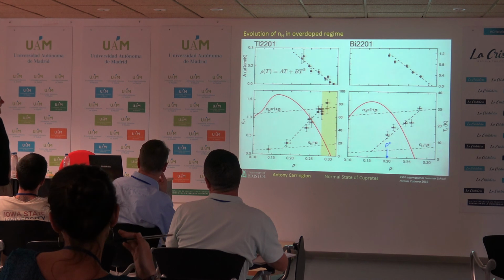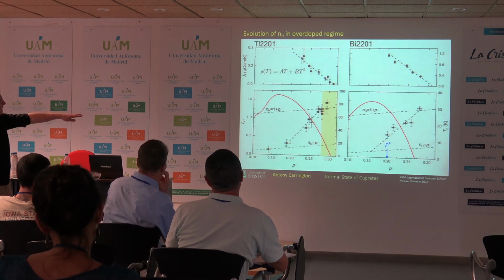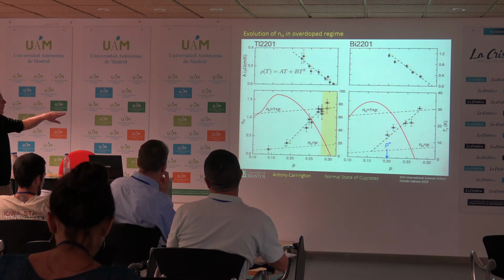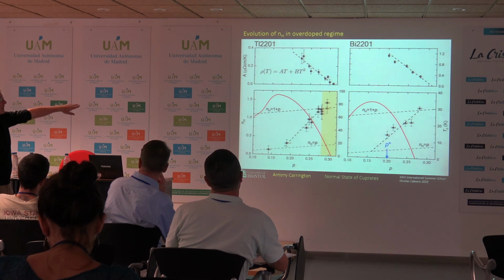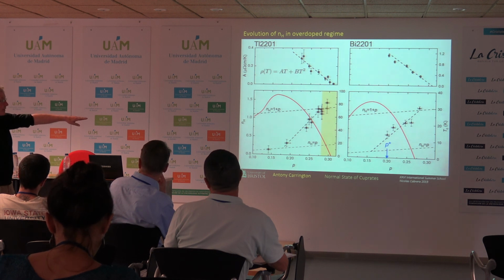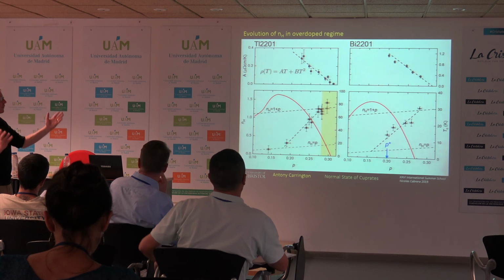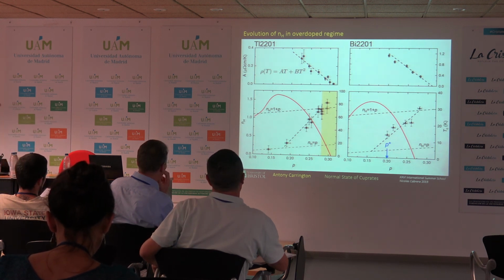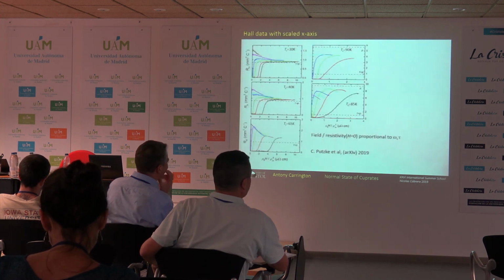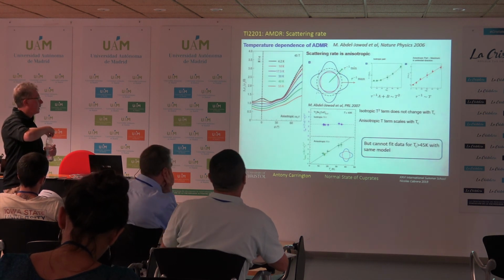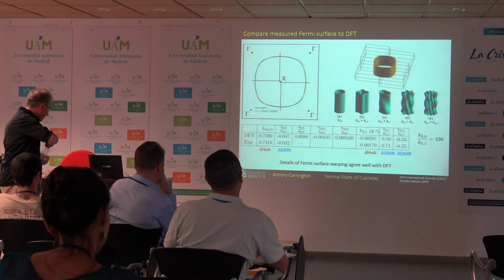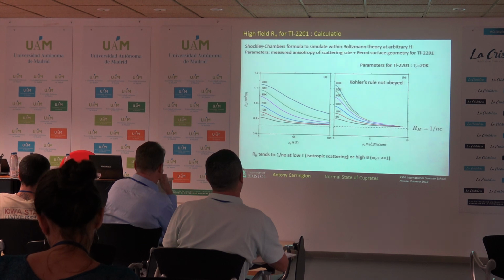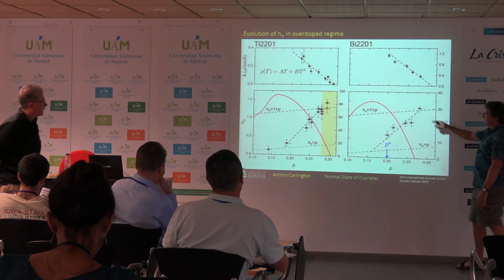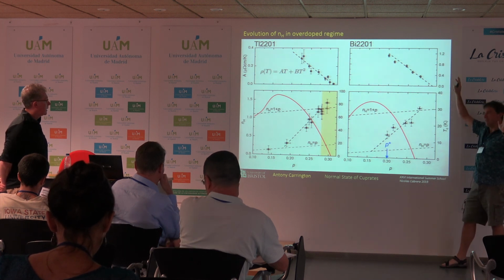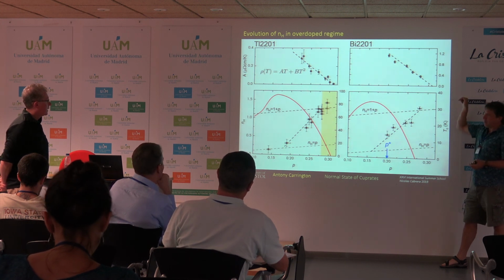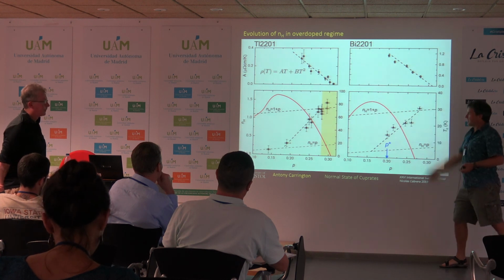Can I suggest, so after you showed us this beautiful sequence of studies, in conclusion, you said that there's no charge density wave, which certainly is a perfectly valid thing to say for thallium-2201. But I think there's tons of evidence for a charge density wave in bismuth-2201 from dozens of groups. True. So there is a CDW on the right-hand side. Yes. CDWs can do strange things, and it depends on exactly how it reforms the Fermi surface. But in the underdoped case, it does the opposite to this. The CDW makes the Hall coefficient change sign, which means that RH tends to 0, which means that this tends to infinity. So it doesn't make it go down, it makes it go up.